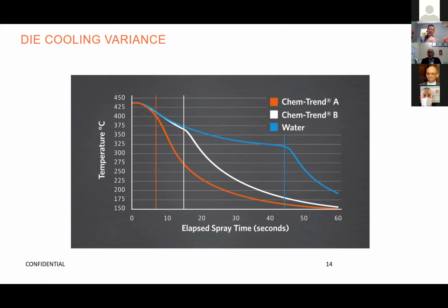It's all thermal balance—energy in and energy out. We've got to keep that in balance. If we take out too much, we have a cold die and get all those cold die defects. But the other point is, when used as designed, you get high performance and differentiated performance. Of course, if you take these and over-dilute them with water, take your dilution way high, what's it going to do? It's going to perform more like water. So you take a die lubricant intended to perform a certain way, over-dilute it, and all of a sudden you have the performance of water.